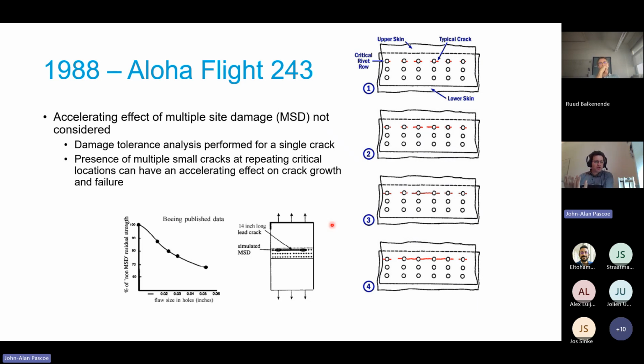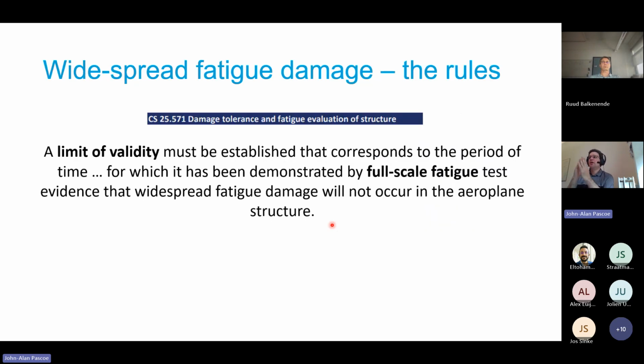And that means this damage tolerance approach doesn't work, because the small crack may be too small to detect easily, but as soon as it links up, you suddenly have this jump in the crack length. And so you cannot inspect in that small time interval before the crack links up. So that limits the damage tolerance approach. And therefore, what you now see, if you look in the regulations, this is one of the European regulations. There's one section on what they call damage tolerance and fatigue evaluation of structures.